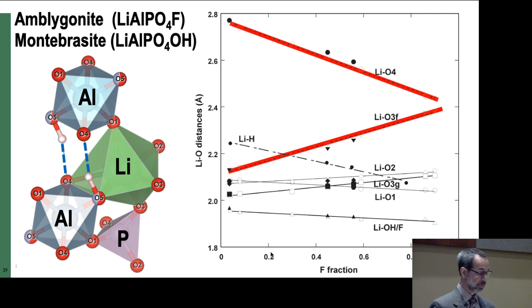And so the way we understand this case is that in the one end member for montebrasite, you have the hydrogen bond forming to O4. Of course, the bond lengths shift quite a lot, and the lithium O4 strengthens as the hydrogen bond to O4 is removed, and at the same time weakens the lithium O3 bond. And then you end up with positional disorder associated with that site. Kind of interesting.